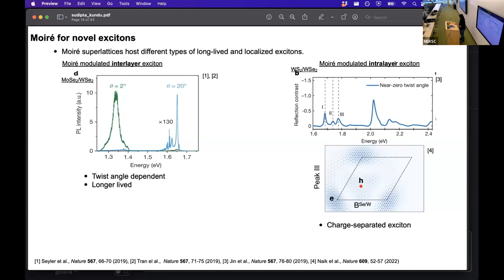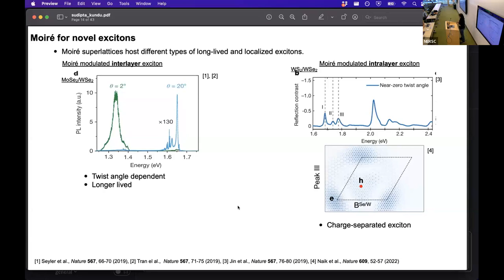There is another type of exciton which we call intralayer exciton. In this exciton both the electron and the hole are in the same layer, they are often tightly bound, and they can be optically very bright, but the problem is they are very short-lived. In WS₂-WSe₂ moiré, another type of intralayer exciton has been discovered where the hole and the electron are spatially separated, so they become longer-lived, which is good for experiment or application. By the moiré pattern we can tune the exciton properties as desired.